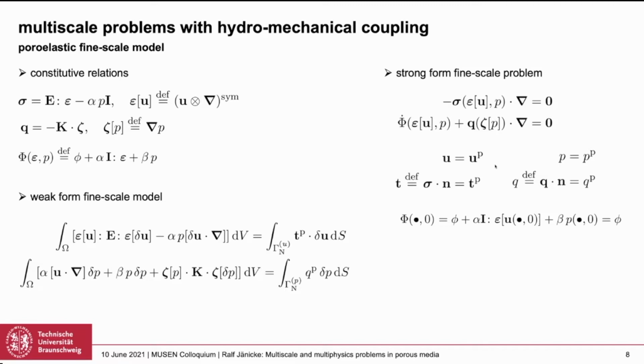So the model I'm introducing here is very simple. It's linear poroelasticity. It means it's a linear but transient problem. If we consider cracks, these equations don't change terribly much. If we make certain assumptions for the pressure diffusion in the cracks, if we assume that there is a transport following Darcy law, which basically means that you assume, for instance, a quadratic velocity profile in the crack, then the continuity equation we derive here will be very similar to that one for the porous elastic medium. That's why I skipped that to keep it simple.